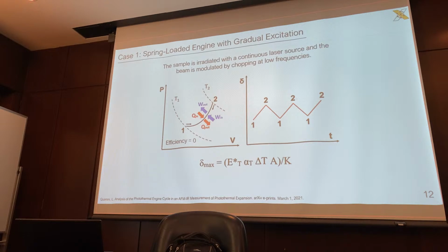So the first case that they go over is a spring-loaded engine with gradual excitation. This corresponded with many of the older techniques of AFM-IR, where they had a laser that was on constantly, and it was essentially chopped at very, very low frequencies. So the material was excited and then chopped at lower frequencies. In this case, we are only moving between 2 points, this 1 and 2, from T1 to T2 on this PV diagram.